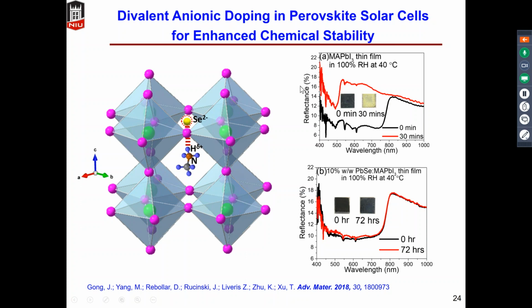And we further expanded this idea to some other ions by doping divalent ions, such as lead selenide. So we used lead selenide as the precursor and doped approximately 10 weight% of lead selenide in the precursor solution of MAPbI3. And we found this thin film exhibits much better water tolerance with respect to the conventional MAPbI3. Within 72 hours, at 100% relative humidity at 40 degrees C and under light illumination, we see just a tiny bit of change of its